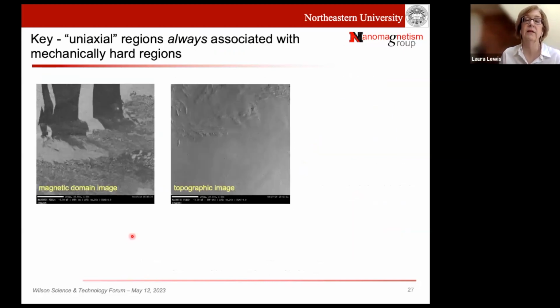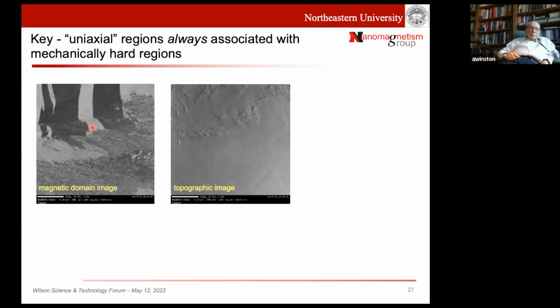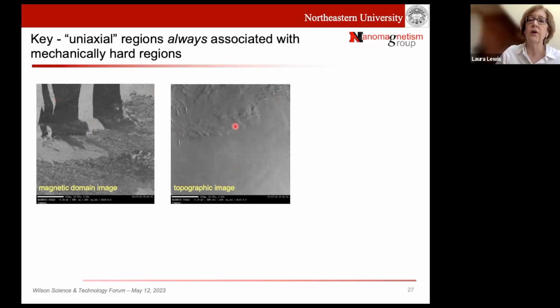And this is, I think, the most compelling image. If you look at the left-hand side with our magnetic domains, and you look at the right-hand side, this is just the topography. You can see there is an exact one-to-one correspondence between this special black and white and this hard, very difficult to polish sample. I was very fortunate that Stefan, their technician, all he does is polish. He polished the sample for 6 hours, a lot more than the 40 minutes my students did. And therefore, this is a very hard to polish region. We know that this chemical order makes things very hard. And this is actually how meteoriticists identify tetrataenite in meteorites, because it's very resistant to polishing. So that was kind of interesting.